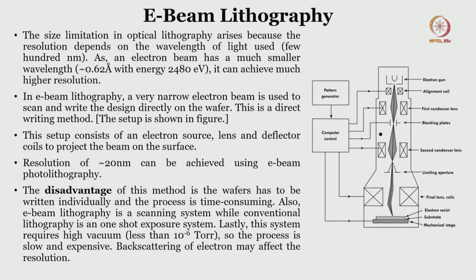Now let us quickly understand what E-beam lithography, or electron beam lithography, is. You can see here that the electron gun creates a very high energy electron beam, which is passed through the alignment coil and through the blanking plates to the secondary condenser lens and then the limiting aperture, so that when it passes through the final lens and coils, the electron beam will scan the substrate which is coated with the resist, and there is a mechanical stage which will move depending on the area which we want to expose.